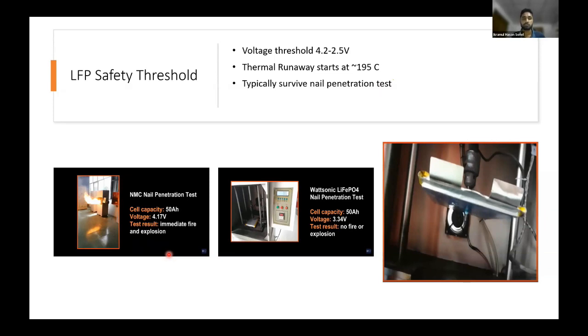As I have told you already, it can withstand up to 200 degrees centigrade, almost 195 degrees centigrade. And there is a very unique and extreme test, which is the nail penetration test. As you can see here on the right side, in that test, normally an iron nail penetrates inside the battery. This battery is penetrated directly, radially, from one side to the other with a nail, and it is done inside a chamber. On the left side, it is NMC. After this nail penetration test, within seconds, it caught fire in the left image.